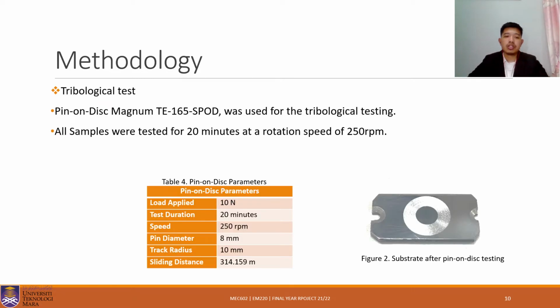Lastly is the tribological test. Pin on disc TE-165-SPOD was used for the tribological testing. All the samples were tested for 20 minutes at a rotation speed of 250 rpm. As you can see in table 4, is the pin on disc parameter, which is applied load 10 Newton. Test duration is 20 minutes. Speed is 250 rpm. Pin diameter is 8 mm. Track radius is 10 mm. And sliding distance is 314.159 meter. Figure 2 shows the substrate of the pin on disc test.